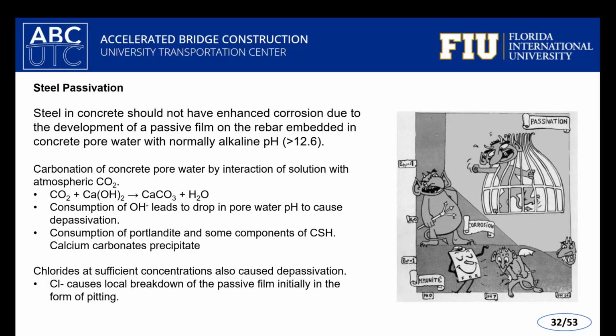So notably, chloride ions are notorious for being able to break down that passive film. When you have these aggressive salt environments, whether from the seawater itself or just atmospheric spray near the coastlines, chlorides are able to penetrate through the concrete cover, through the concrete pore water, eventually diffusing with enough concentration at the steel interface at a sufficient amount where they can start breaking down that passive film.